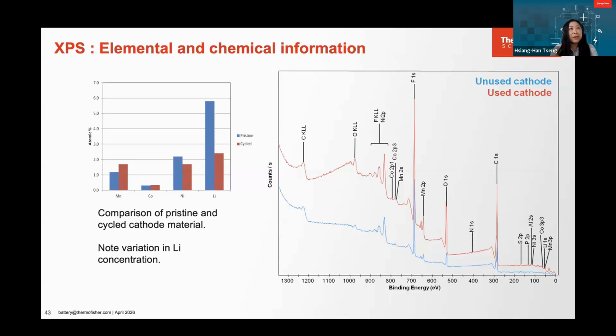On the figure on the right-hand side of this slide, you can see the relative intensities of the manganese, cobalt, and nickel components, which appear to be quite similar between the two samples. However, you can immediately notice that the lithium component appears to be quite a bit less, corresponding to around 40% of that seen in the pristine cathode. This behavior is very expected in a sample taken from a charged cell, because the higher lithium concentration should be associated with the anode rather than the cathode, reflecting a depleted lithium level compared to the pristine cathode.